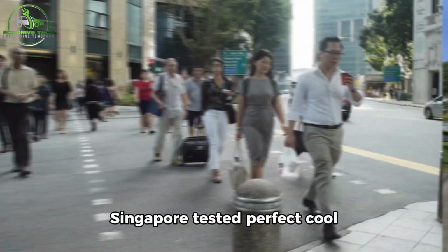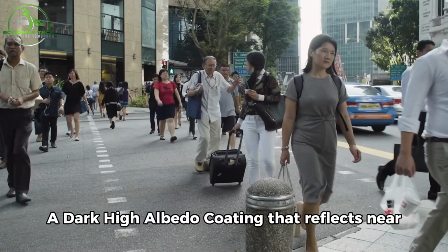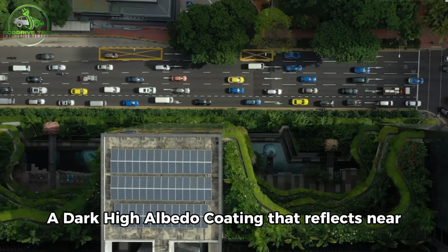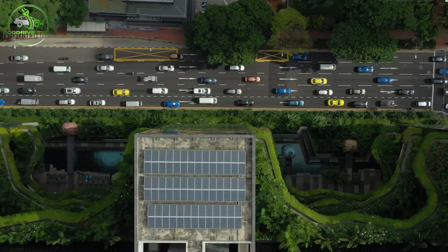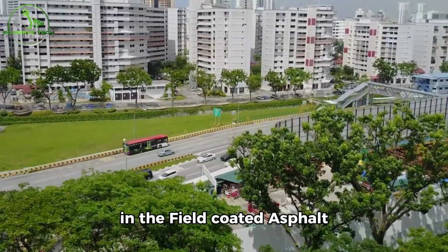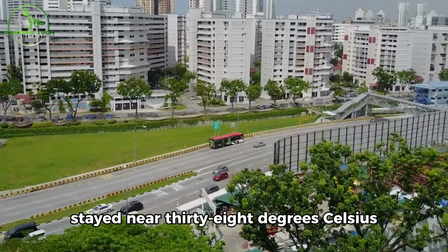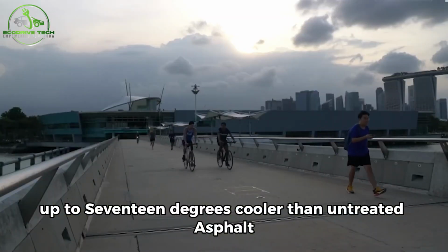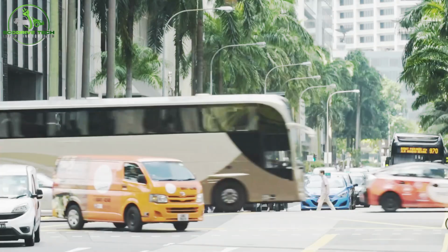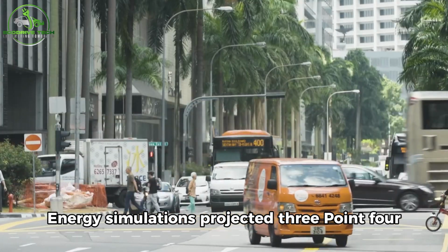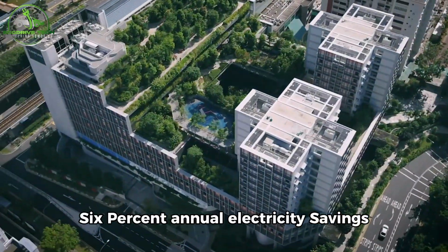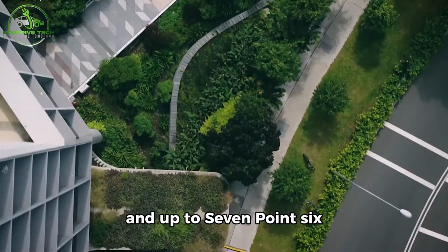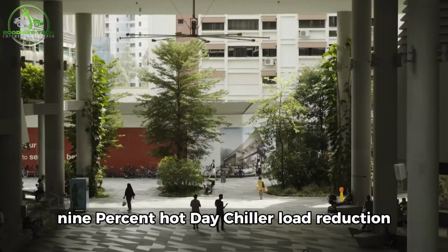Singapore tested Perfect Cool, a dark high albedo coating that reflects near-infrared radiation. In the field, coated asphalt stayed near 38 degrees Celsius, up to 17 degrees cooler than untreated asphalt. Energy simulations projected 3.46% annual electricity savings and up to 7.69% hot day chiller load reduction.